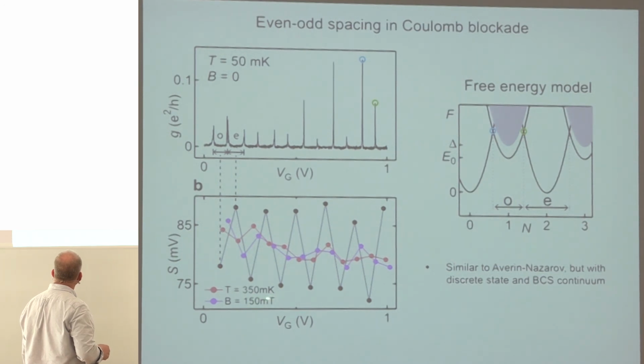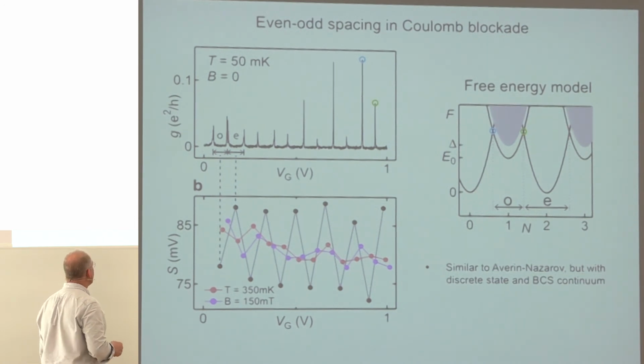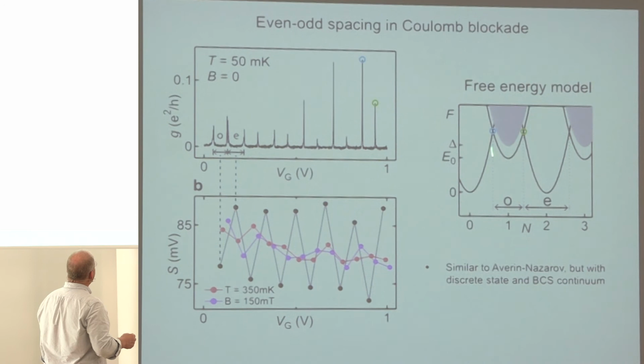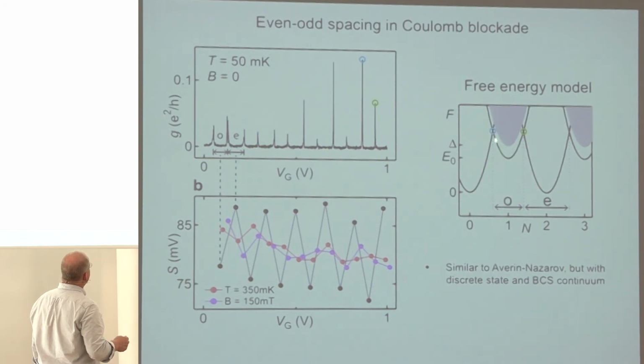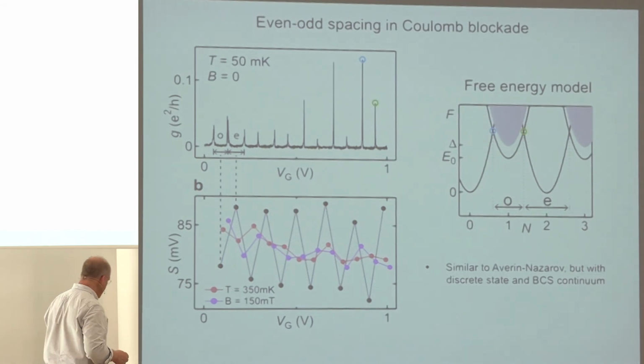Neither of these temperatures are the critical values. That is, it's still superconducting at 350 millikelvin, and it's still superconducting at 150 millitesla, but the even-odd structure has gone away. If we analyze the problem, very similar to what was done by Averin and Nazarov, but including a discrete state for this bound Andreev state plus a continuous density of states, we can find the crossing points for the location of the odd versus the even Coulomb blockade peak.